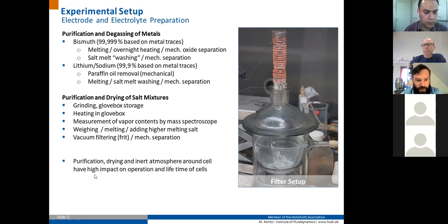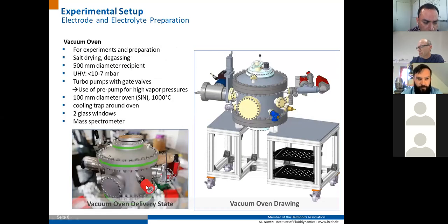And one comment, the purification, drying, and especially the inert atmosphere around the cell have a very high impact on the operation and the lifetime of the cells we observed. If the preparation and the materials are not very high purity, you could expect the cell to fail within hours of operation due to corrosion by the impurities and different side reactions, which then led to, for example, a short circuit of the cells.